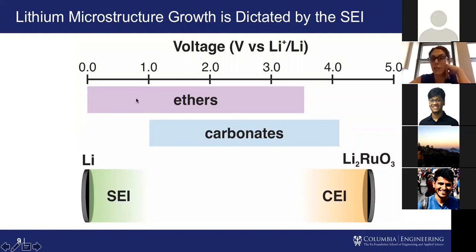We think that ethers might be one promising way to stop this microstructural growth because they have a better stability window at lower voltage. And I'll talk a little bit about that in the second half of my talk. But basically, what we want to know is how we can change this electrolyte formulation to change lithium microstructural growth in a battery and make them safer.